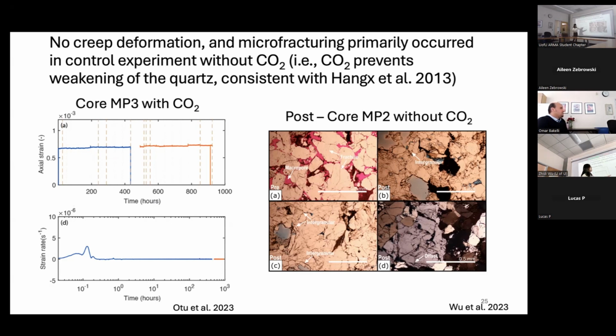And here, same, in the thin section, we notice something: even in the control sample, the sample without CO2 injection, we see some microfractures. That indicates those microfractures were not caused by CO2; they already occurred originally in the sample. Could be because of compaction, or something to do with the depositional history.